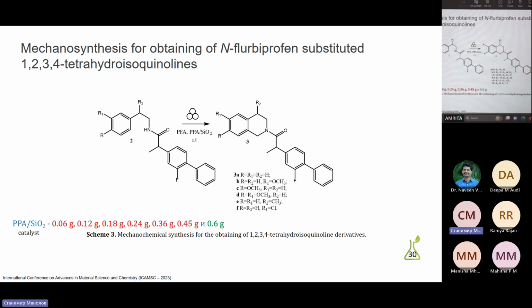Following the reaction completion, the resulting powdery reaction mixture was transferred into a flat-bottomed flask and dissolved in dichloromethane. The mixture was then transferred to a separating funnel and washed twice with water. The organic phase was subsequently dehydrated using anhydrous sodium sulfate, and the solvent was distilled off.